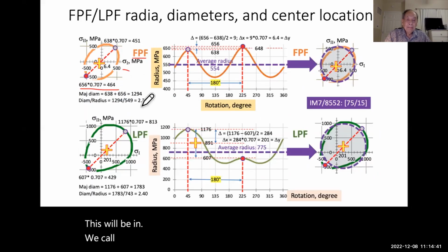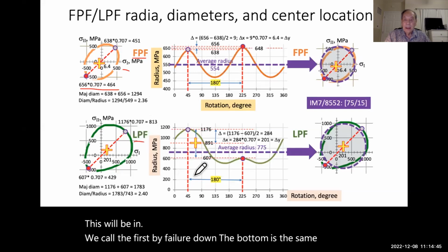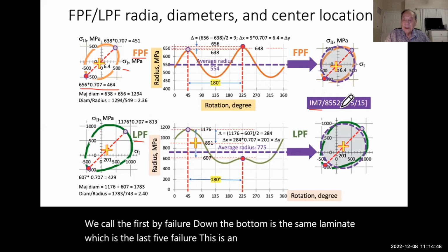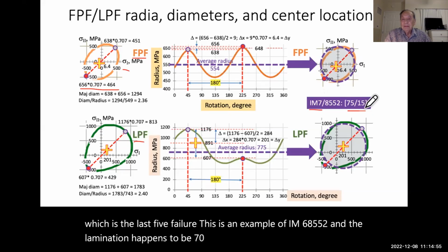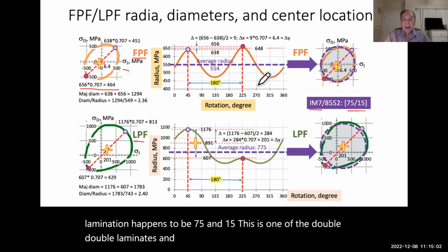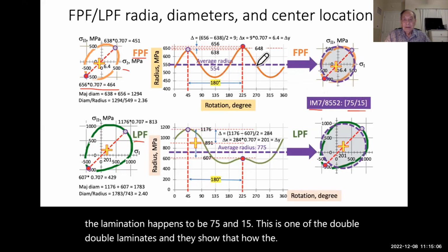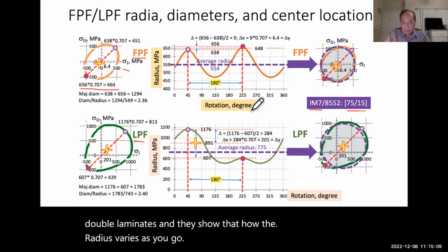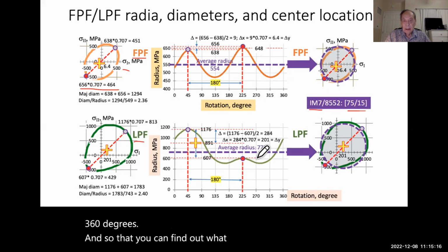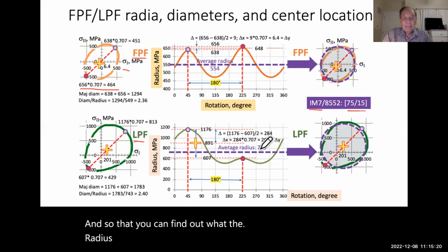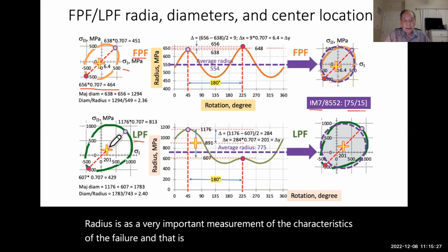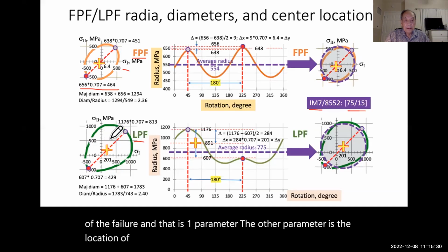This we call the first ply failure. Down at the bottom is the same laminate, which is the last ply failure. This is an example of IM7 8552, and the lamination happens to be 75 and 15. This is one of the double-double laminates, and they show how the radius varies as you go 360 degrees. And so you can find out what the radius is, as a very important measurement of the characteristics of the failure. And that is one parameter. The other parameter is the location of the center, as indicated by the cross here.